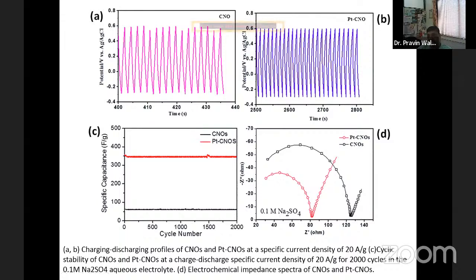So what exactly happened in your material after decorating it with platinum? Here is the impedance spectra - impedance spectra of CNO and impedance spectra of platinum decorated CNO. You can clearly see this spectra is quite big, and this is reduced drastically. This suggests that the charge transfer resistance of that electrode has drastically changed.